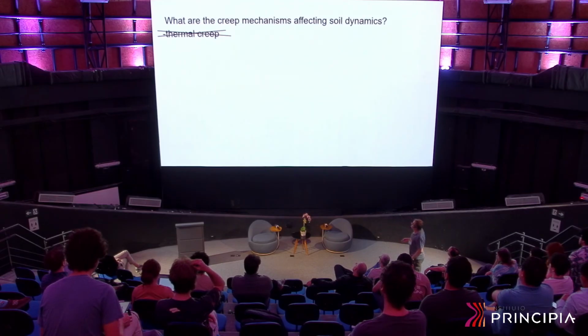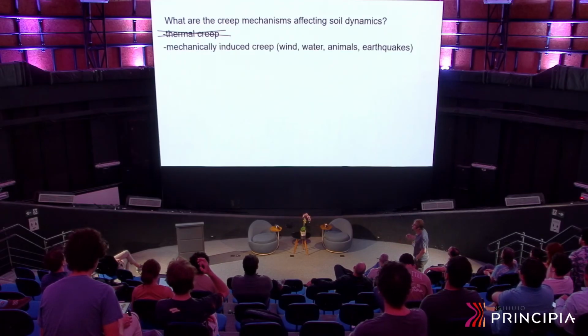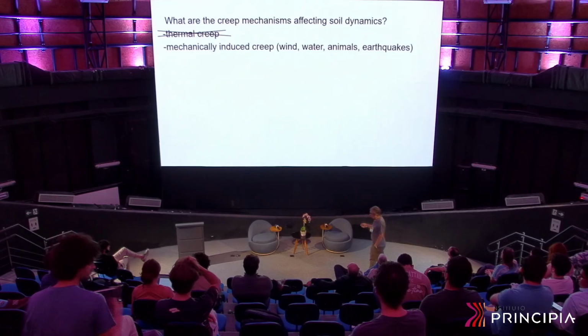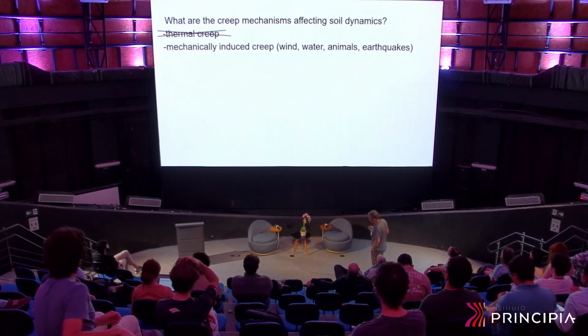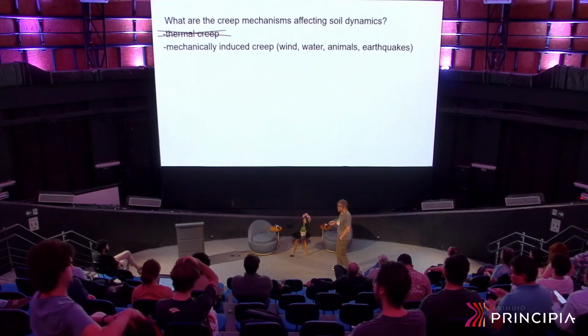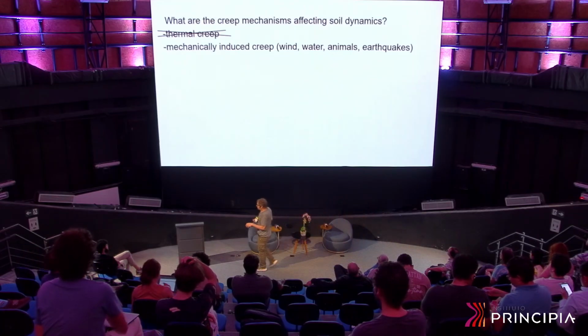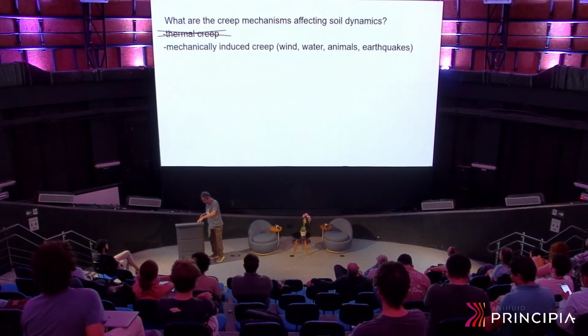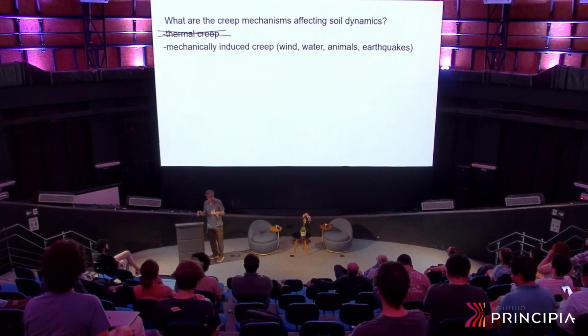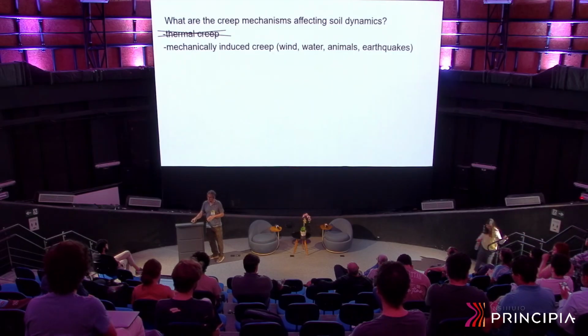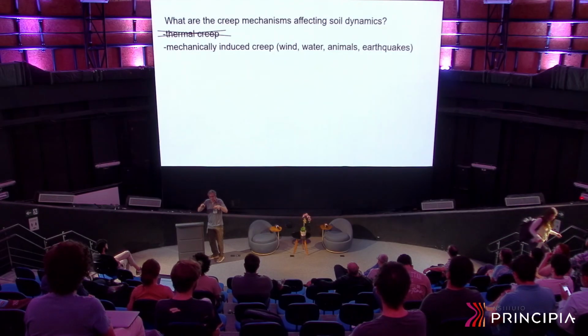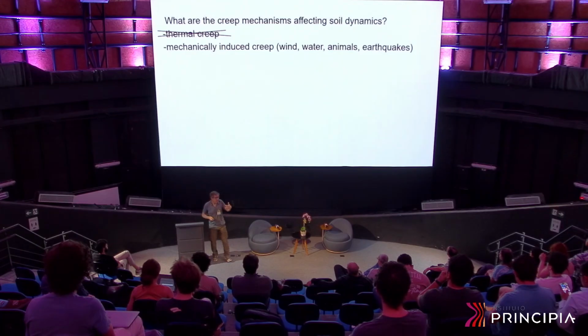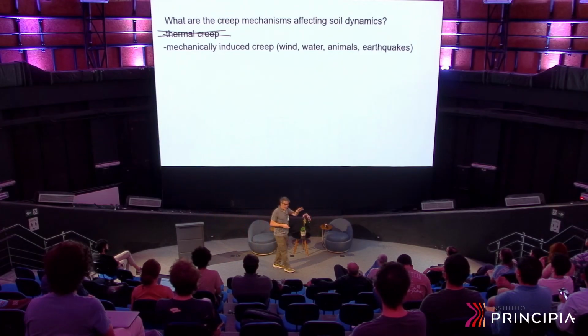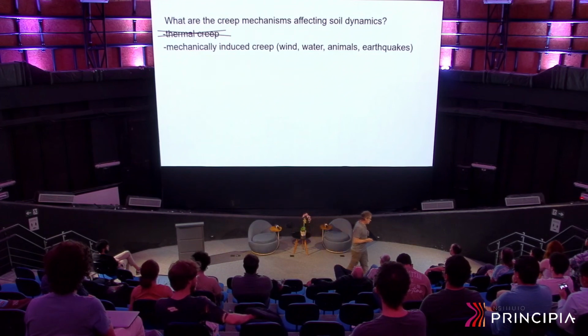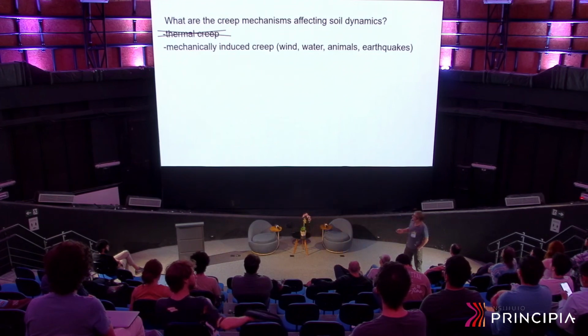Geophysicists and geomorphologists have known for a very long time that mechanically induced creep, namely mechanical activation caused by a number of reasons that can occur in this material, can produce this kind of behavior. If you take a heap of sand, put it onto this table, and leave it alone, probably it will stay for a very long time. But if you start to tap on the table, it's clear that it will slightly move down and flatten. This is a dynamical phenomenon that can occur. I'm not denying its importance, but this is not the phenomenon we decided to study,